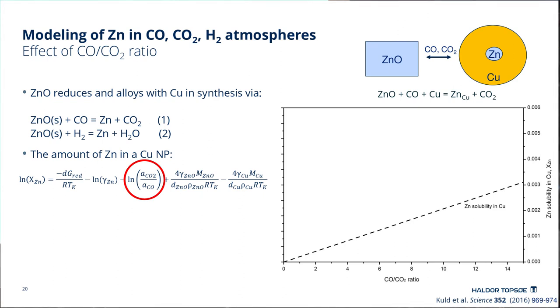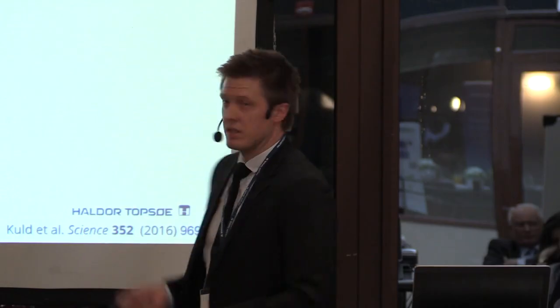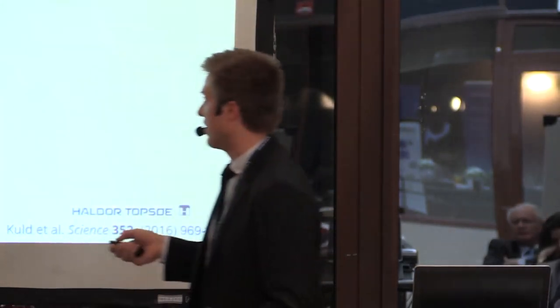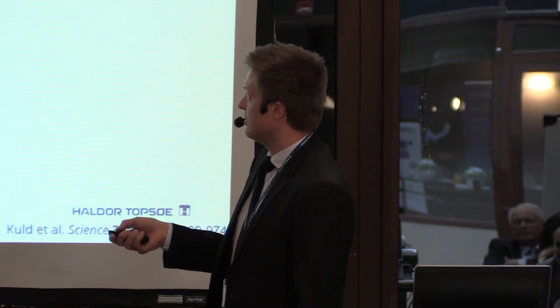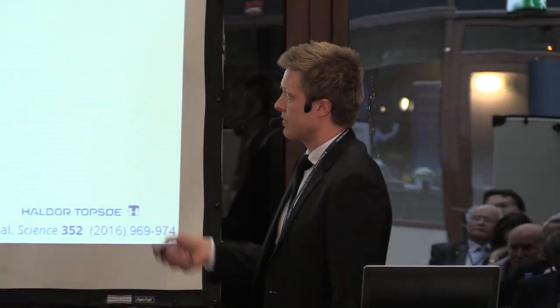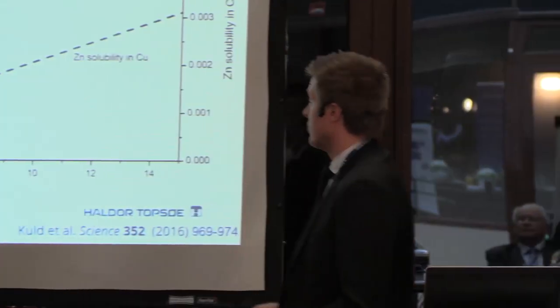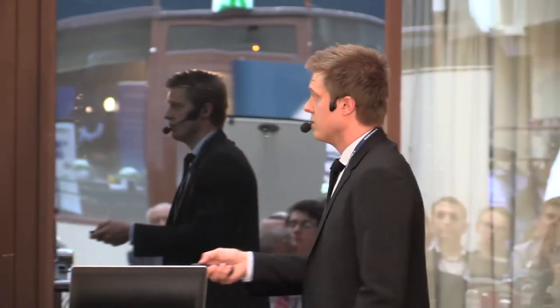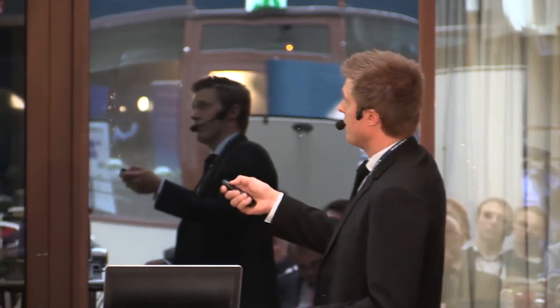The thermodynamic expression of how much zinc you can dissolve in your copper particles is given by this expression. Don't worry, I won't go into detail with how it's derived today, but I'll point your attention to this term here, which contains the CO and CO2 ratio. This can be used as a descriptor for the reduction potential of the synthesis gas, so to speak. So here in this plot, you see the CO and CO2 ratio, or the reduction potential of your synthesis gas, and here you have how much zinc you can dissolve in your copper particles.